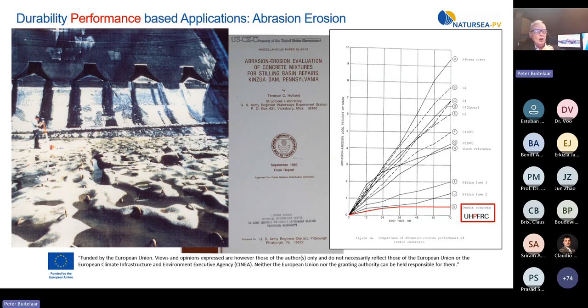The specified unreinforced 1,540 cubic meters of special design DSB concrete by my former colleague Eigil Sørensen, with a thickness of 30 centimeters and with a compressive strength of 90 MPa, was placed in sections. I would have designed another solution by using the best tested UHPC as a 50 millimeter thin bonded overlay on the DSB concrete, like what we do in the Netherlands in locks and sluices.